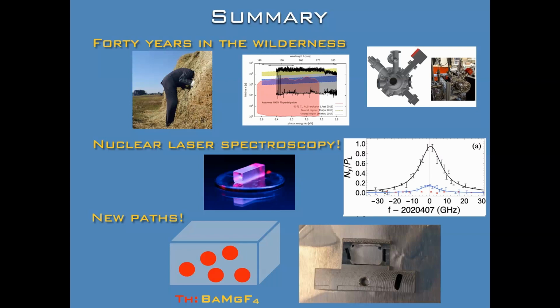Yes. So what's the underlying reason why some crystals have such a low participation? Yeah, so we've been working very hard on this problem of what this quenching mechanism is. My suspicion is that it's hyperfine mediated nuclear electron interaction, and it's probably very sensitive to the electron density of states of these defects nearby. My guess, and it goes against what the DFT says, is that if you grow a crystal in the thermodynamic minimum, the participation fraction should be 100%.